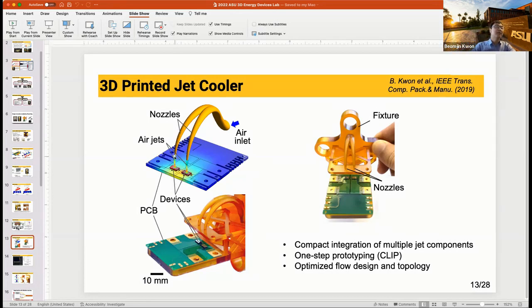And also if the spacing between the nozzle and the heated device is too small, the jet on the surface interacts with the flow at the nozzle. So if you bring your nozzle extremely close to the heated surface, it actually makes the heat transfer worse. But if you put the nozzle too far away from the heated surface, your air jet spreads out and the flow speed is too slow on the surface.